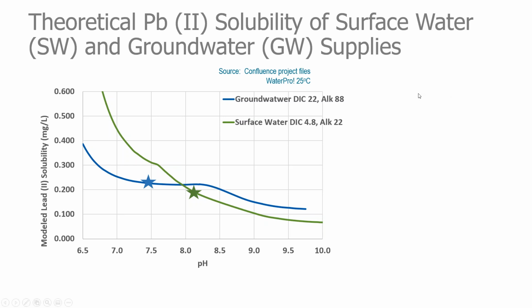So here's a classic solubility curve that I generated for these two waters in particular. The green line shows the solubility of lead as a function of pH in a low DIC water at a DIC of 4.8, and the blue line shows theoretical solubility of lead for the groundwaters. And we can see that because the DICs are different, lead isn't just a function of pH, the DIC really matters. We wouldn't want to match the pHs. If we just said pH is 7.5, then the groundwater would have lower solubility than the surface water, and at high pHs, the surface water is lower than the groundwater.